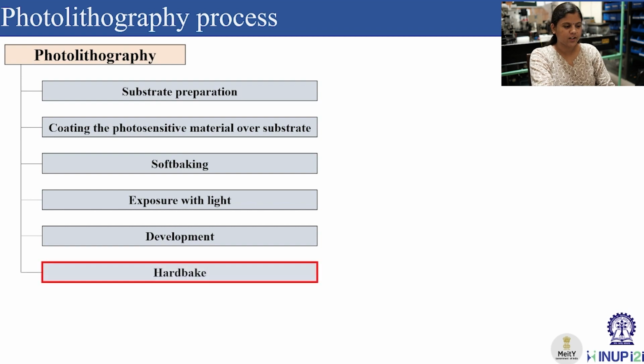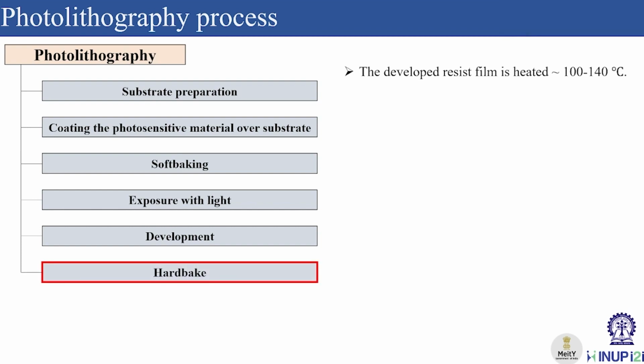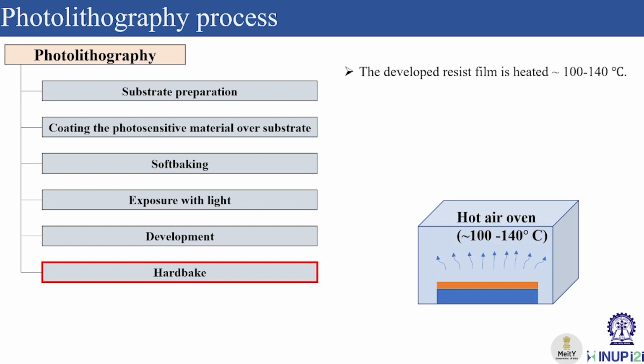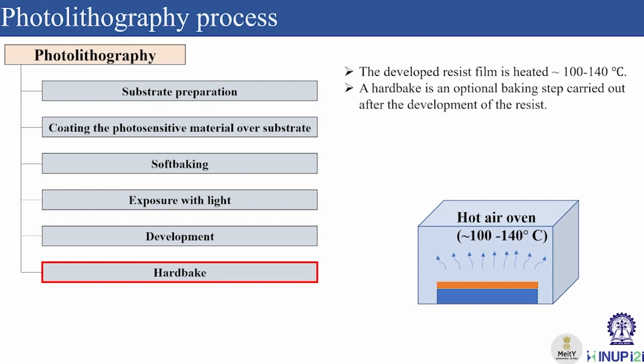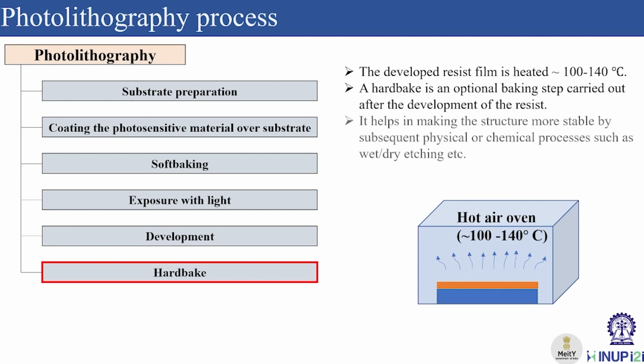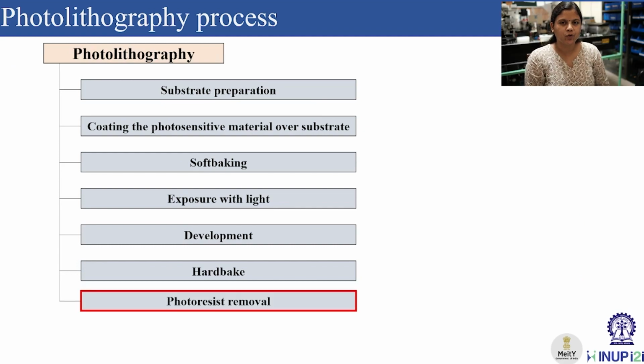After developing the films, the next step is hard bake. In the hard bake, the structure is heated at around 100 to 140 degrees Celsius for several minutes, as shown here in the figure. Now, hard bake is an optional step, and it may not be mandatory, but it is helpful to make the structures more stable for subsequent physical or chemical processes like wet or dry etching, etc. So the next step is photoresist removal.